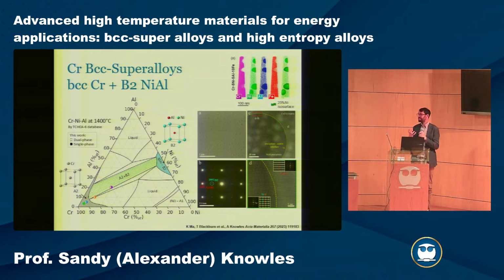That was a real advantage of doing this as part of a consortium and a large-scale international collaboration, in that we're able to do high-resolution TEM, where you can see the atom columns and how things arrange, both in the chromium, in the nickel aluminium, and also at the interface. So we are trying to design specific interfaces, for example, the misfit, how the two lattice planes are coincident, and the misfit in the lattice parameter of the different elements. We can also do things like atom probe tomography, where we can look at the elemental segregation between these different phases.